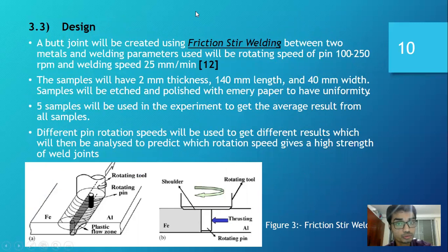So in my design, I have chosen friction stir welding to create a butt joint, and I will be using the welding parameters used by Watanabe in his research. There's a rotating speed of pin 100 to 250 RPM and welding speed 25 millimeter per minute. The samples I will be using will have a thickness of 2 mm, 140 mm in length, and 40 mm in width. And before carrying out the experiments, I will do etching and polishing of my samples with emery paper to have uniformity. I'll be using 5 samples with different rotation speeds of pin and welding speeds to get the average result from all samples, and I will compare those results to find which rotation of pin speed gives the high quality of strength.